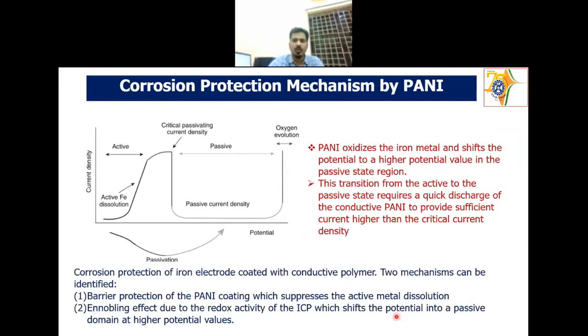So what it is doing is, this is a typical polarization curve for an active-passive material. Generally active Fe dissolution is happening here, then it goes to the passive state, and at more than 1.2 volt oxygen evolution will happen. In the passive state, the metal is being protected. The presence of Pani can take the material quickly to the passive state and get protected for a longer time. That's how the Pani works here. As I told, this is a kind of ennobling effect due to the redox activity of the intrinsically conducting polymer, which shifts the potential into a passive domain at higher potential values.